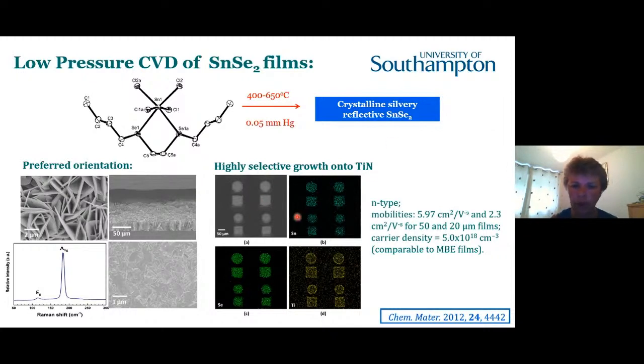And then over on the right here, we have the selective deposition into these patterned substrates. And again, you can see very clearly that in the region where we've got titanium nitride, these yellow circles and squares, that's where the tin selenide is depositing. We've looked at the performance, the electrical performance of these films, and they're comparable to films produced by molecular beam epitaxy, which is one of the best, the highest quality benchmarks for semiconductor materials. So initially we were using these to deposit thin films, and tin diselenide has got a range of interesting applications.